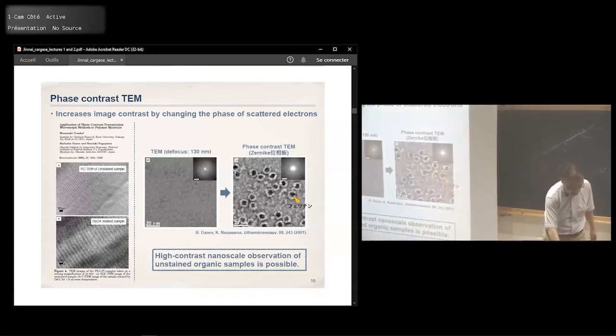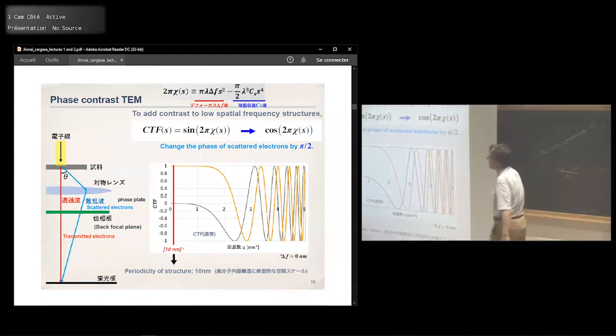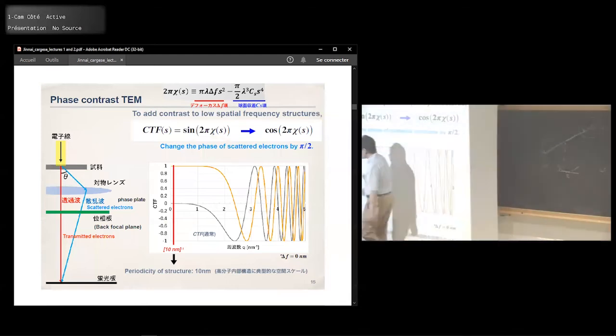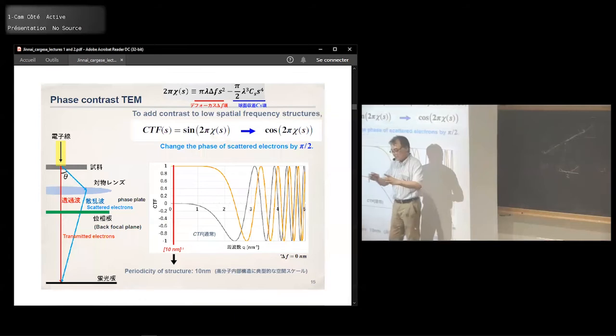But the difficult thing about this phase contrast TEM is that this phase plate has a hole in the middle where the transmitted electron goes through. So you need to finely tune the position of this phase plate so that the transmitted electrons just go through.